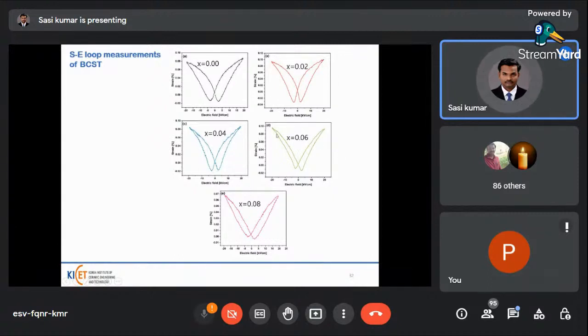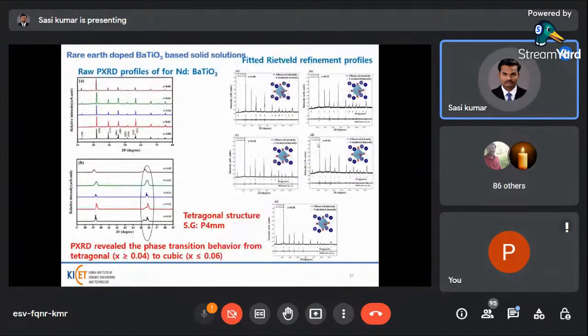Similarly, the x equal to 0.06 composition also possesses higher electrostrain compared to other materials. And then we go for some rare earth doped barium titanate based solid solutions. First one is neodymium doped barium titanate. The XRD profiles for the different neodymium doped compositions show the tetragonal structure with P4mm space group.